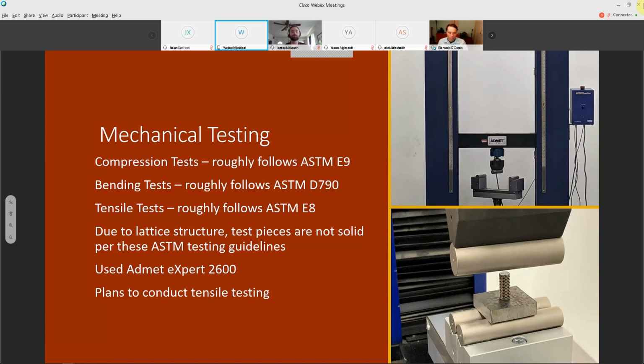So off to mechanical testing. Understanding our printed samples' mechanical properties: compression test, bending test, and tensile test are the tests we prepared our printed specimens for, roughly following the American Society for Testing and Materials standards. Unfortunately, because of our lattice structure printed design, the test pieces are not solid per these ASTM testing guidelines.